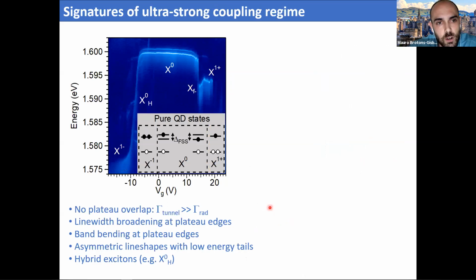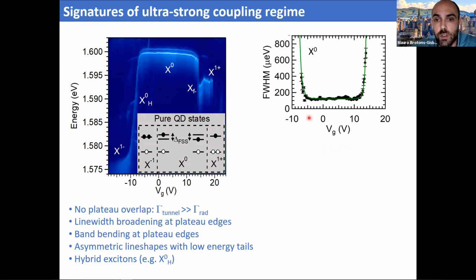But again, there was something else going on here, and there were some signatures giving us clues that there was an ultra strong coupling between our quantum dot and the Fermi sea of electrons. One signature is that the plateaus don't overlap. You can see that this plateau doesn't overlap with this, and this doesn't overlap with this one. We also observed line broadening of the transitions. If we plot the line width of the neutral exciton as a function of the applied voltage gate, you see that in all this region the line width is constant, but as we approach the voltage gate at which tunneling starts, the line width increases.